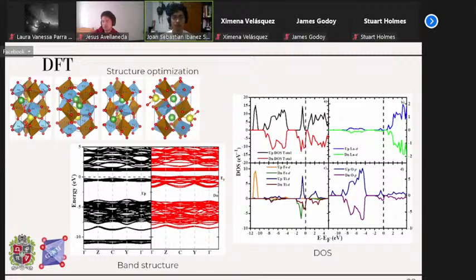And lastly, we haven't been able to analyze fully the density of states, although it is already calculated. But in the image, in the C part in particular, you can see that there is an atypical behavior for the titanium. It has a prevalence similar to that of the iron, and they both are the generators of the ferromagnetic behavior. That would be this part.